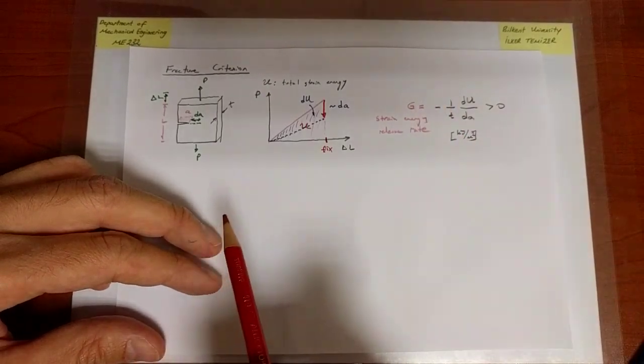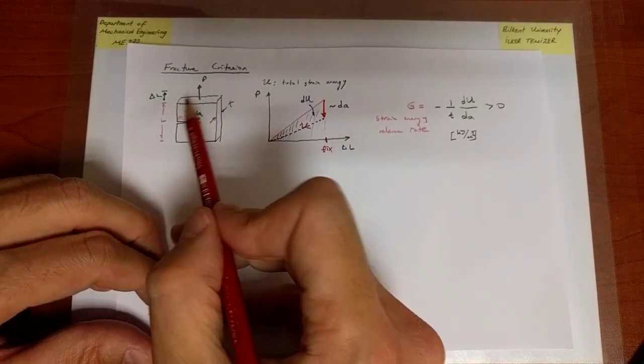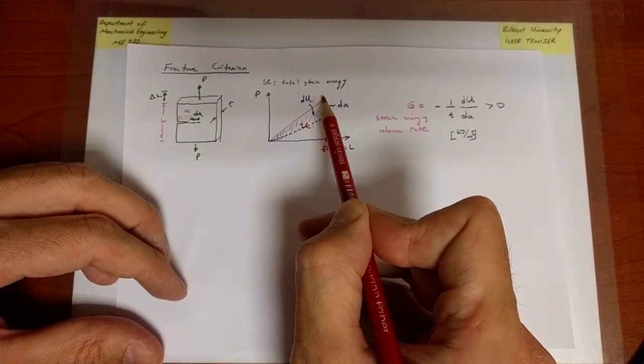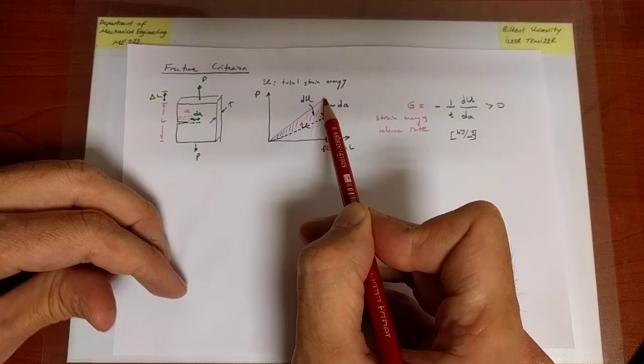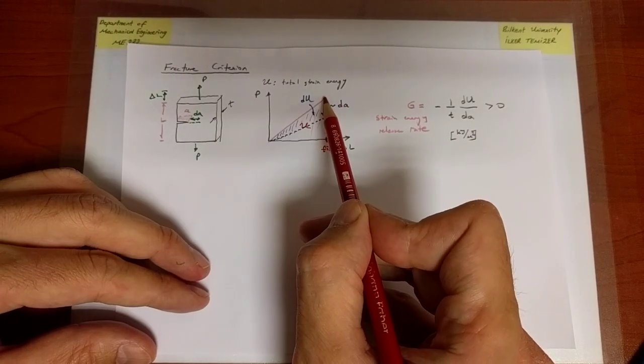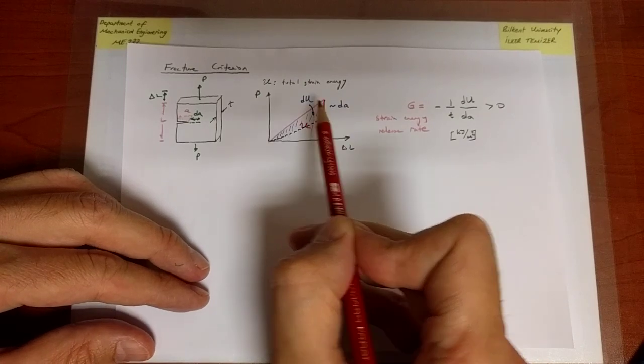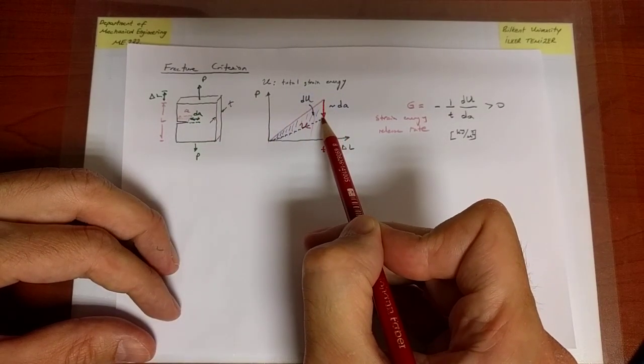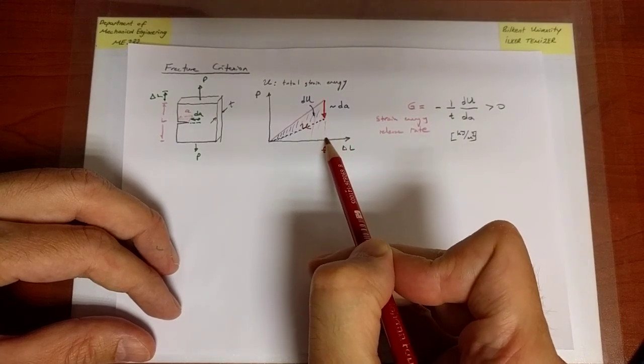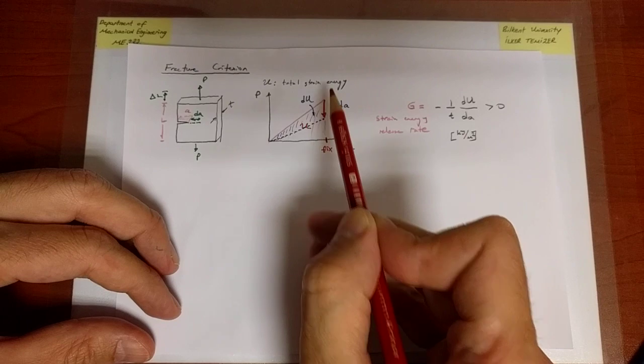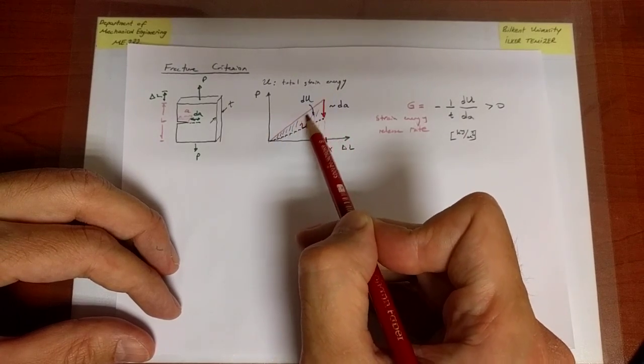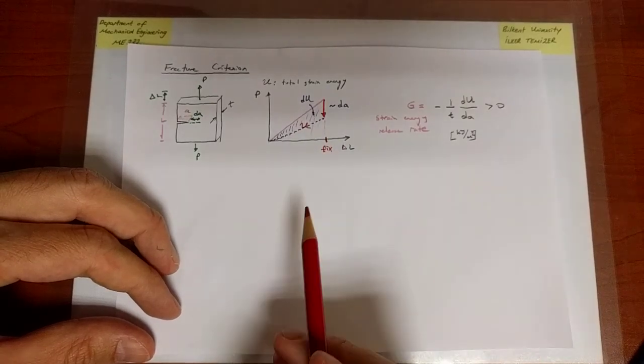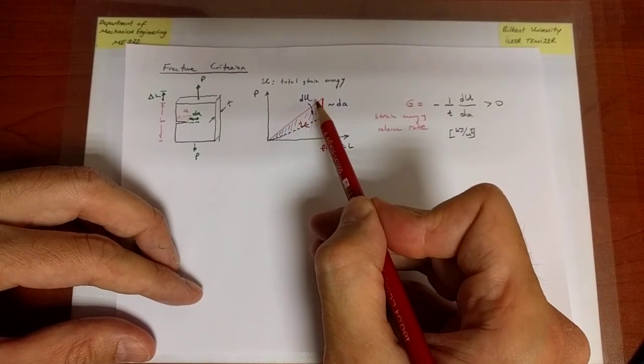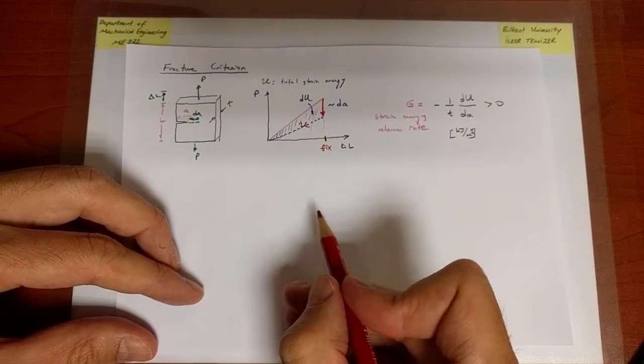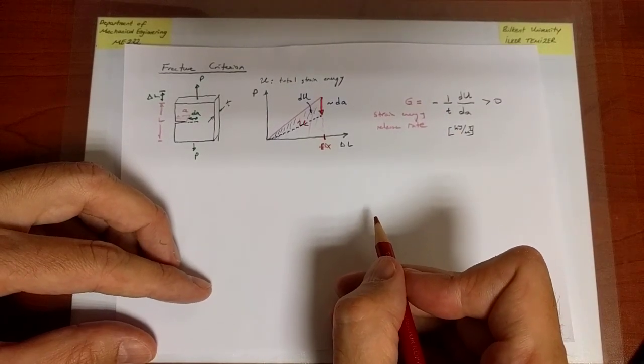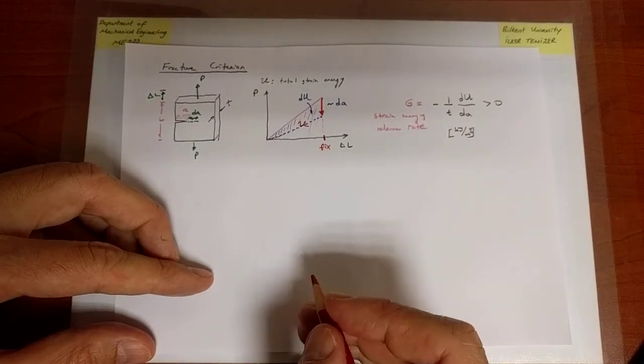Okay, so what was the thought experiment? Let me summarize again. I have a structure, I pull it up to a certain point, the load reaches a certain level, and I assume that the crack propagates, not physically perhaps, but virtually, and therefore the crack size increases as it does so, the cross-sectional stiffness gets reduced and hence the load gets reduced. And because the overall elongation of the plate is fixed, the total energy that has been released from the system is simply calculated by that blue shaded area, and that area, when I scale it properly, indicates the rate with which strain energy is being released from the system. So it's kilojoules per meter squared.